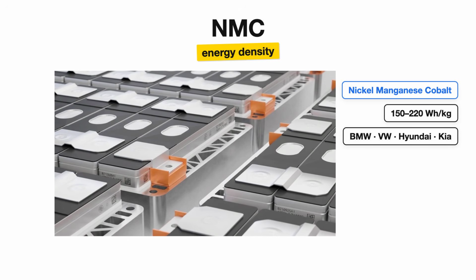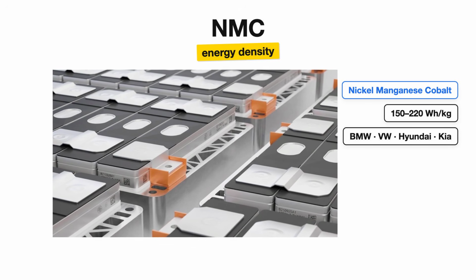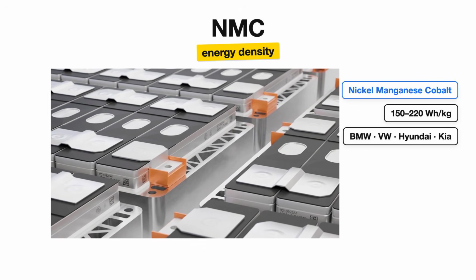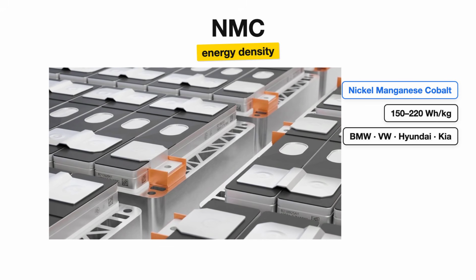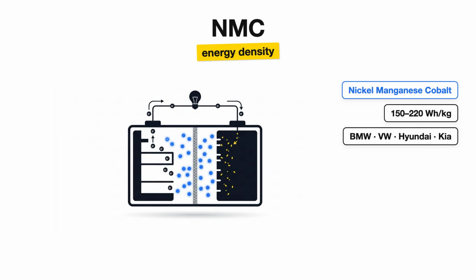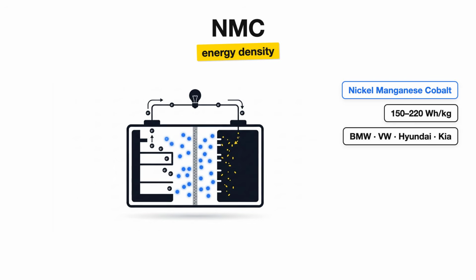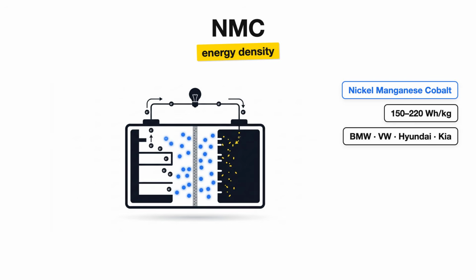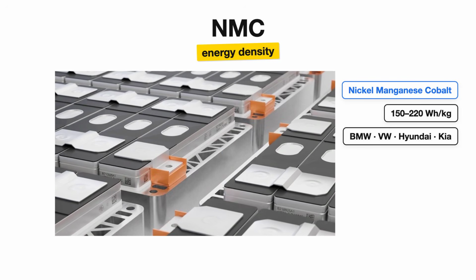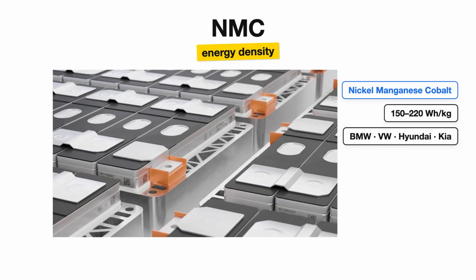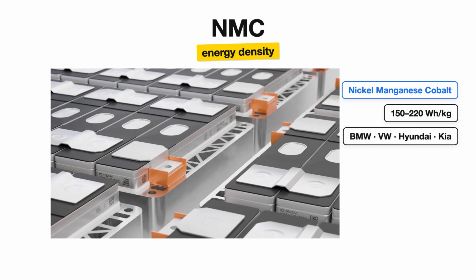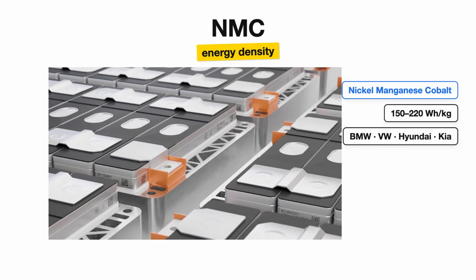NMC comes in variants. NMC 811 pushes nickel to 80% for more density, but that makes the cell more thermally sensitive. More energy in, more heat to manage. The problem with NMC, and with almost every high-energy EV battery chemistry right now, is cobalt. We will come back to that, because it is a bigger issue than most people realize.